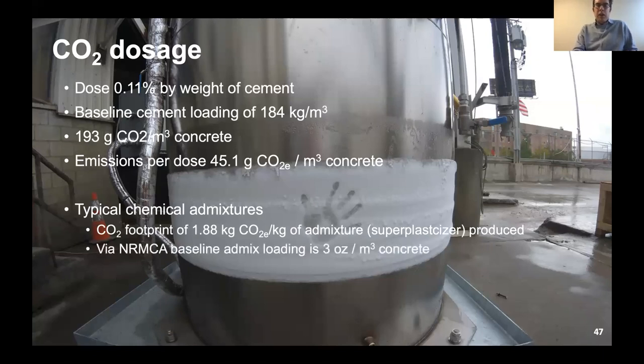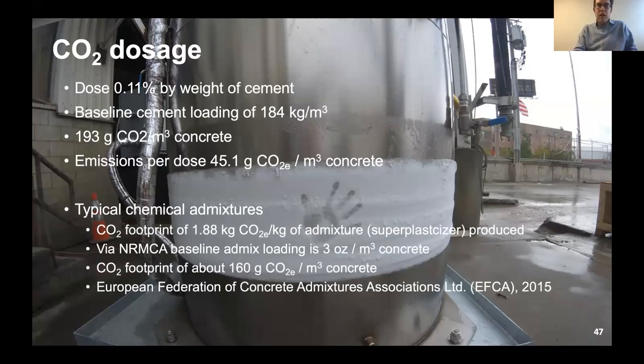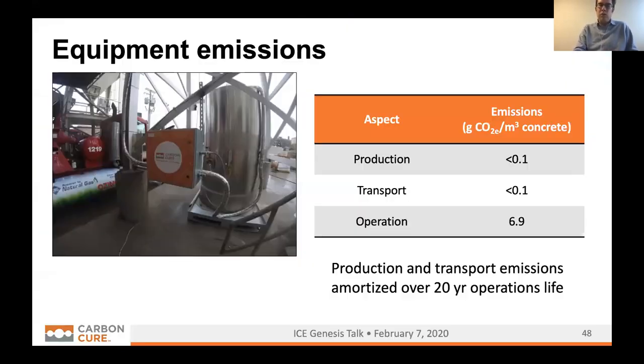And if you look at the National Ready Mixed Concrete Association, they say producers are using about 3 ounces of a given admixture per cubic meter of concrete. So that means your admixtures come in with a CO2 footprint of about 160 grams of CO2. So our idea is that the 45 grams of CO2 to get the CO2 admixture in compares quite well with normal admixtures. So this is a small process emission, but it's not unusual.